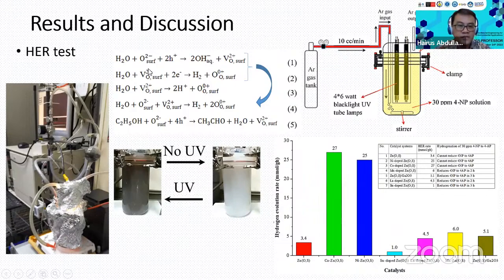And these oxygen vacancies play a very important role in the reaction. They absorb the water molecules and make the reaction easier, right? Water can be oxidized to form a proton, and then the proton is finally reduced again by the photoexcited electron to form hydrogen. Then we have proved that the reaction can be done in pure water, without the hole scavenger.